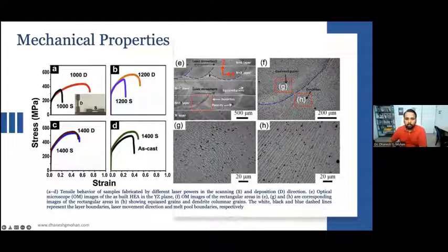I have marked here between three layers. There are three areas. The first area, as shown over here, is G, that is equiaxed. Most of the grain structure formed is very fine and very equiaxed. And here we have the H area. In the H area, dendrites are formed. Dendrites form when the temperature is high. That means at 1200 watts, the temperature in that particular region is very high.